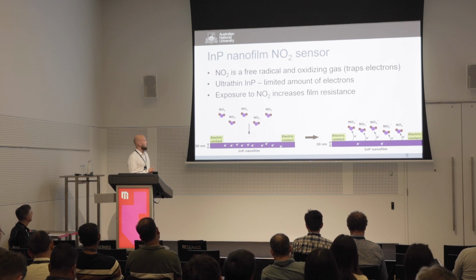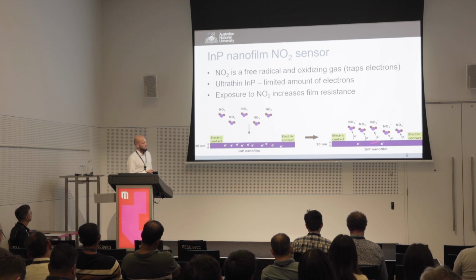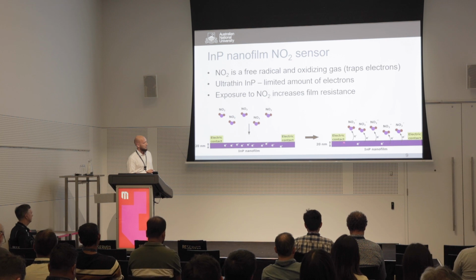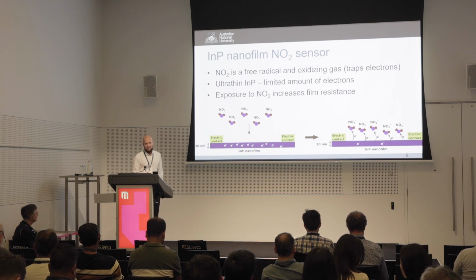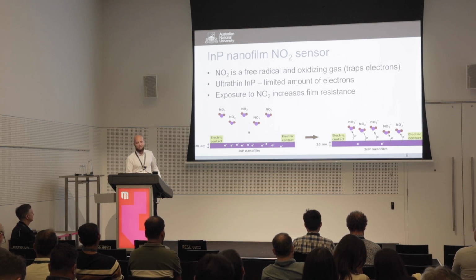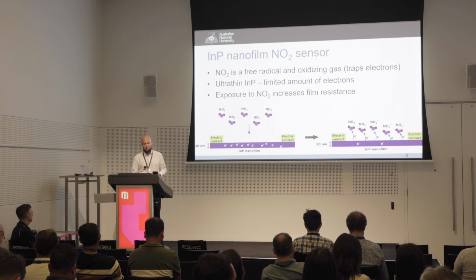So when we have these NO2 molecules interacting with the indium phosphide film, they will trap a certain amount of the electrons out of the film, and that will change the resistance between these electric contacts. And the change in the resistance will correspond to the concentration of the NO2 in the atmosphere.